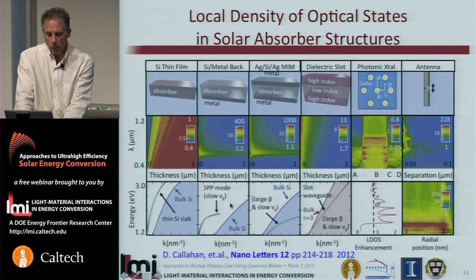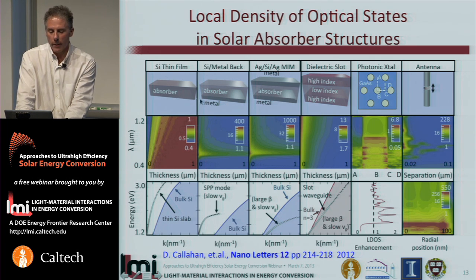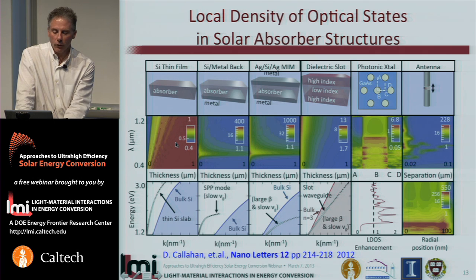And this is a rather complicated plot here that depicts a number of motifs for thin film solar cells, including just a thin film of silicon with a metallic back reflector, silicon clad with 2 metal layers in a slot format, a silicon absorber clad by dielectric materials, a photonic crystal, and then finally a photovoltaic absorber coupled inside an optical antenna. If we now compute the local density of optical states and compare that to that of a bulk material, we can find, for example, in a thin film of silicon that the local density of optical states is always less than that of the corresponding bulk.